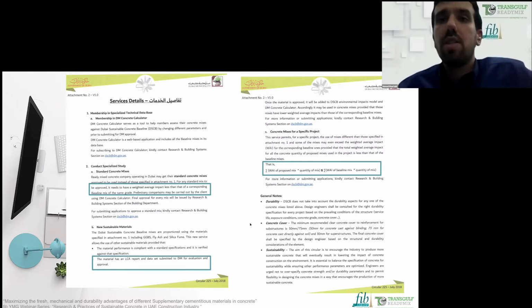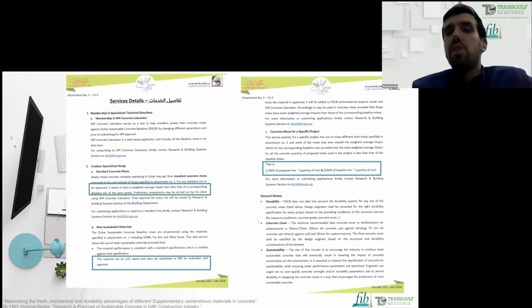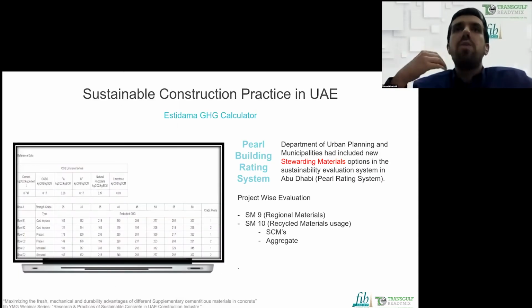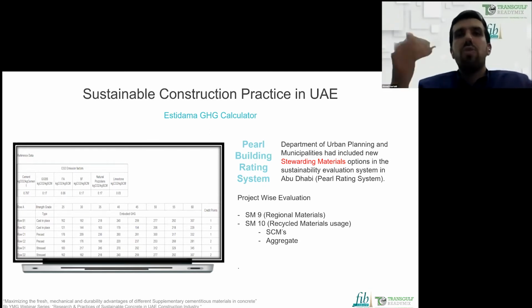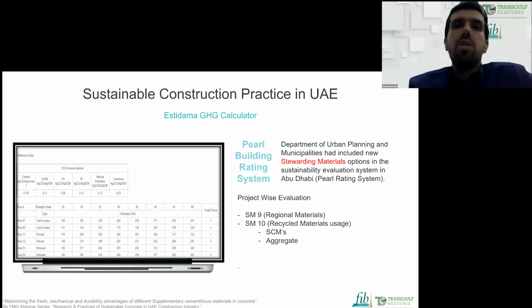And the last option, as discussed before, is calculating the weighted average impact for a concrete structure or for a whole project. For example, in this approach, a blinding concrete can go without Portland cement, or grades 20 and 30 can go without supplementary cementitious material, but where there is a huge volume of one of the concrete mixes, GGBS or fly ash or any kind of supplementary cementitious material can be added, then the overall weighted average will reduce for the project. So looking from the BOQ point of view and trying to reduce the CO2 emissions from the project.